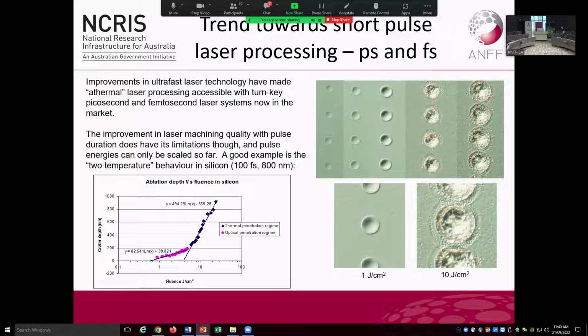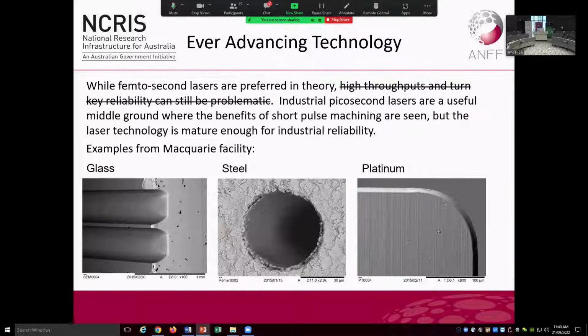But we're doing it like the reverse of 3D printing, where you build something up from the bottom up. We're etching from the top down by removing small layers of material each time, while trying to preserve the quality of the feature that we're leaving behind. And this is some of the examples where we're doing this. Now, I used to give this slide talking about picosecond lasers, because the femtosecond lasers to do this weren't really industrially reliable 10 years ago. But that's not the case at the moment. My next slide, I'll explain what we're doing. But these are the sort of quality features that you're getting with these ultra-short laser pulses.